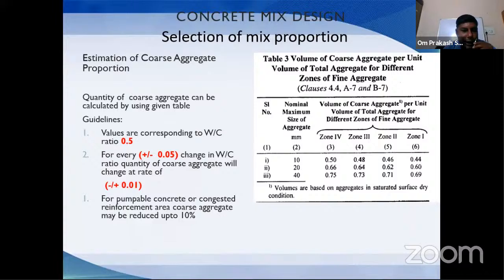So how can we find out the quantity of aggregate? In IS 10262, Table 3 is given, where, according to sand zone, zone 1, zone 2, zone 3 and zone 4, and for the maximum nominal size, the percentage of coarse aggregate is given. We have sand of zone 2, and we are using 20 mm maximum nominal size aggregate, meaning our aggregate maximum size is 20 mm, not more than that. So how much percentage of coarse aggregate should be in concrete? 62%, that is 0.62. Means 62% will be coarse aggregate, that is more than 4.75 mm size, up to 20 mm, and 38% will be fine aggregate, that is sand.